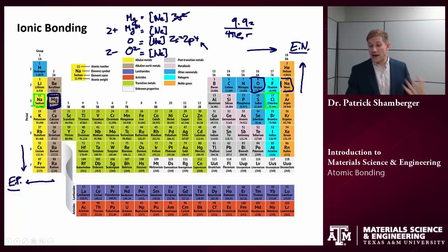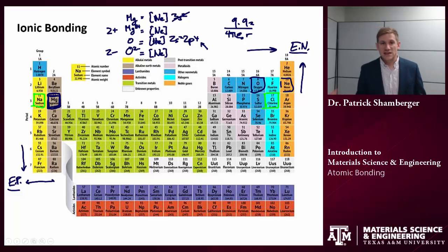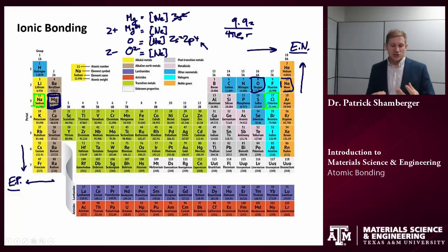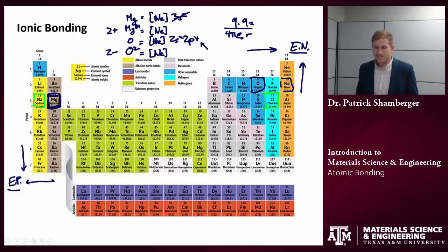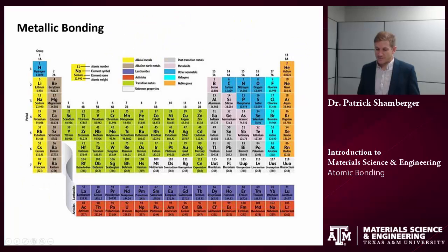So again, an ionic solid is a collection of ions. They have largely given up or accepted electrons to achieve more stable ground states. And then those particles are charged, and so there's some electrostatic interaction between them. Ionic bonds tend to be very non-directional because, again, that Coulombic potential is a radial potential. It doesn't matter based on a particular orientation. So that's an example of an ionic solid.